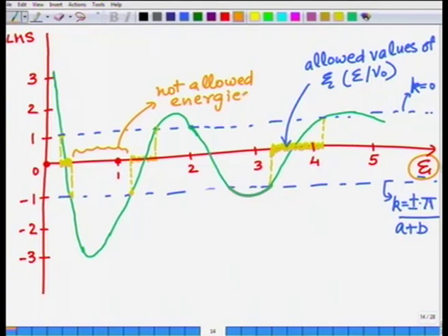So, that is now the first time we are seeing that metals had no band gap, free electron theory could possibly describe them. Now, you begin to see, when you start introducing periodic potential, not realistic yet, but the approximate periodic potential, then you can see the band gap begins to emerge. And that is the characteristic of a semiconductor. So, I wanted to show you where the origin of the band gap is.